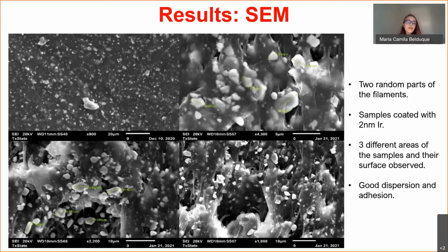There is clearly a good adhesion between the matrix and the strontium ferrite, and although magnetic particles tend to attract each other, there is homogeneity in the particle dispersion of both filaments. No particle clusters were observed, and additionally, the images show a particle size ranging from 1 to about 6 microns, which can affect later the magnetic properties and the 3D printing process.